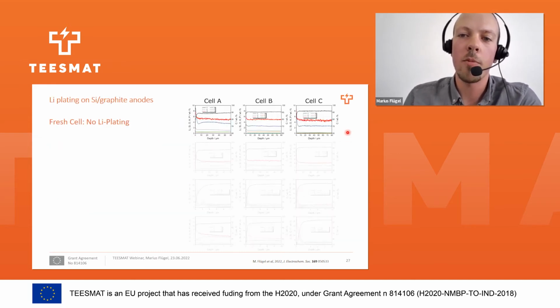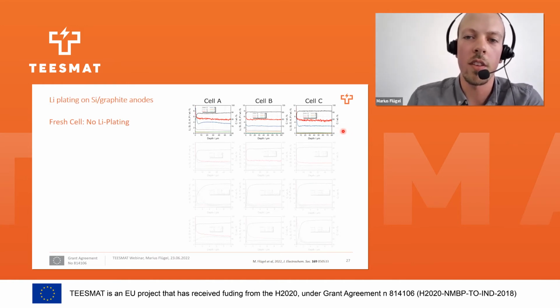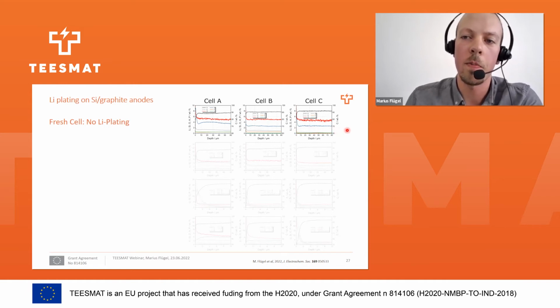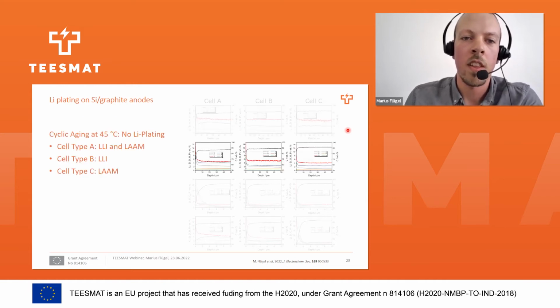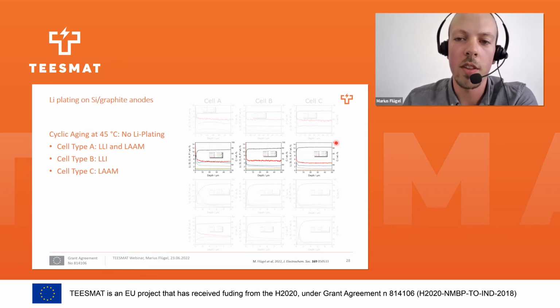The GD-OES depth profiles of the fresh cells revealed also that all those cells contain silicon, and we saw a low amount of lithium in the anodes. After aging at 45 degrees Celsius, we didn't see any lithium plating, but we saw an increase of the amount of lithium in the anodes.